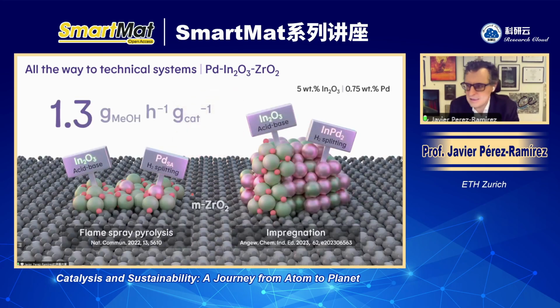So the architecture of that catalyst that was in that bottle could be different. And you can see here two different architectures, one prepared by flame spray pyrolysis on the left, on the right prepared by simple impregnation. These two architectures actually render an equally effective material, displaying a space-time yield of about 1.3 grams of methanol per hour per gram of catalyst, which is actually very high. The material in technical form contains 5% of indium oxide and a small amount, 0.75% palladium.